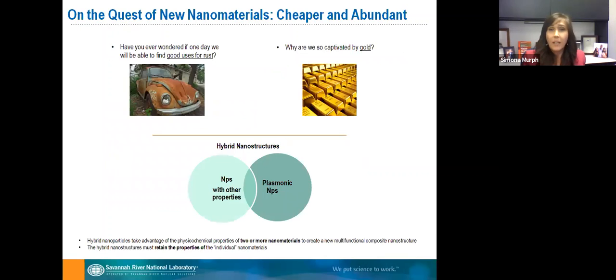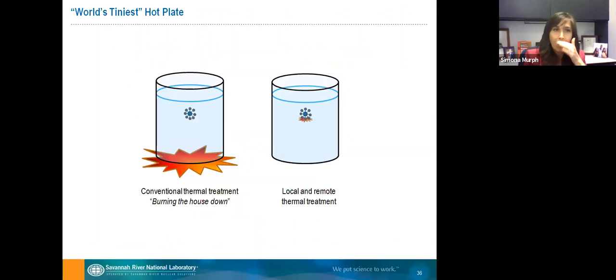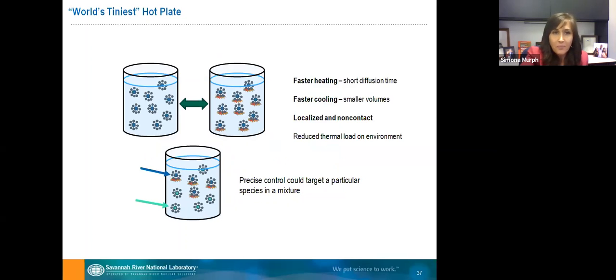So are we there yet? The alchemists tried this forever, right? To transform any metals to behave like gold. So what we did, we coupled the iron oxide rust with some of the gold nanostructures, and we tried to create the world's tiniest hot plate. All the time when we're heating something, you're heating the vessel, you're heating the environment, and then you get to the nanoparticles that you want to heat. So how can we create better localized and remote heating that is more efficient for this reaction path? We said, hey, we can do it with nanoparticles. When you shine light on these nanoparticles, they get hot and they can release the heat in the surrounding media.